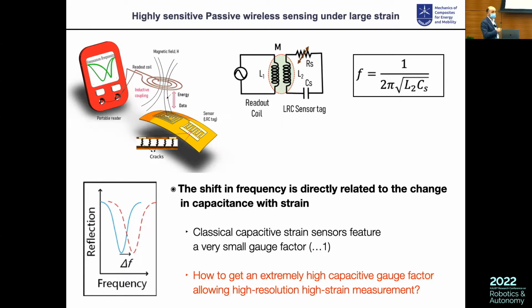So the way we develop this is that we are developing RFID patches. That means a resonating system, an LCR system. If you have a resonating system like this, you can interrogate it by electromagnetic coupling. And you know that when you have this coupling between the interrogator and the sensor, there is a resonance frequency that depends on the capacitance of your system, right? And the way a capacitive sensor usually works is that when you change the capacitance of the sensor, you get a shift in frequency and you measure this shift of frequency. And if the change of capacitance is related to the change in strain, your shift in frequency is a way to monitor your strain, right?